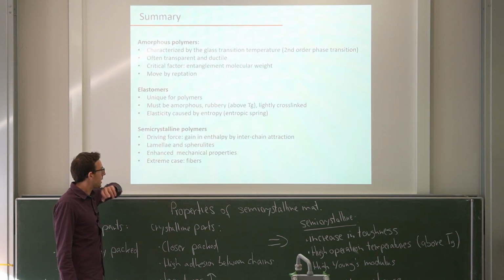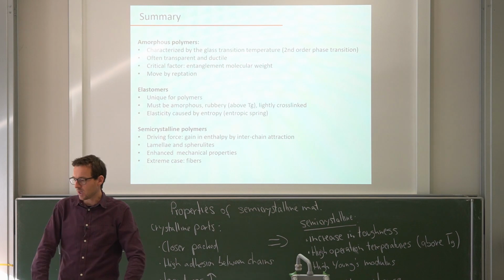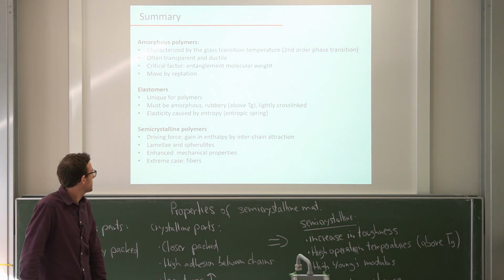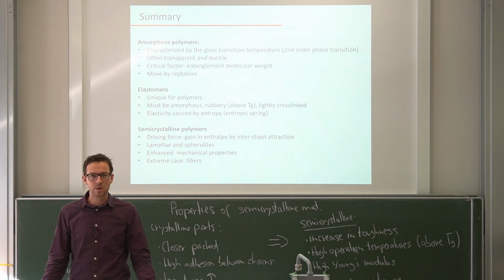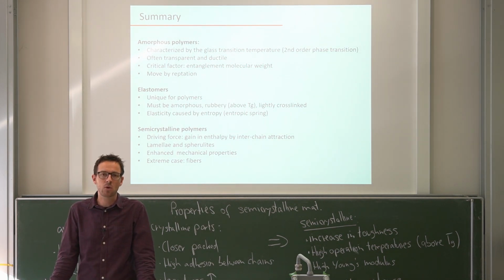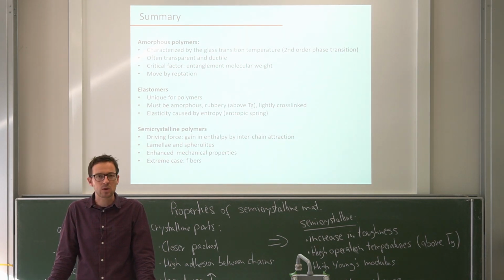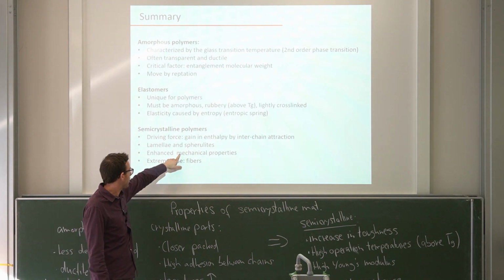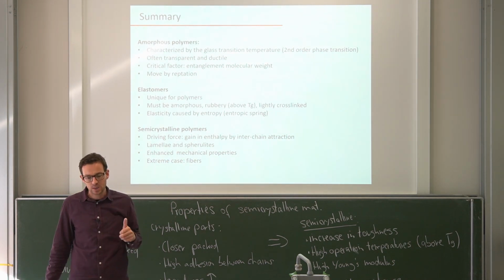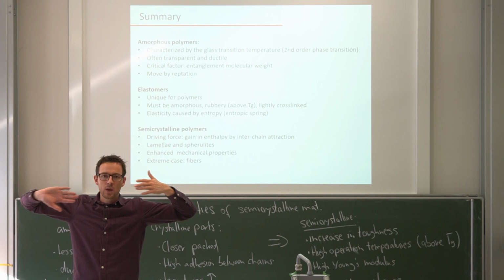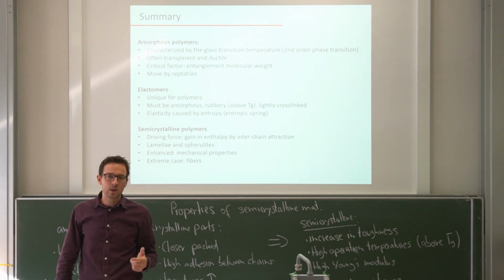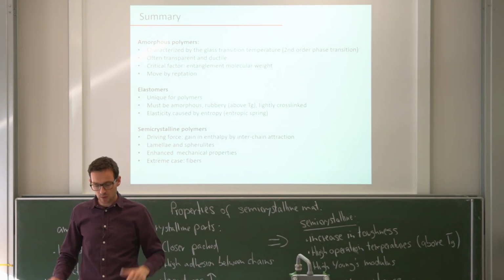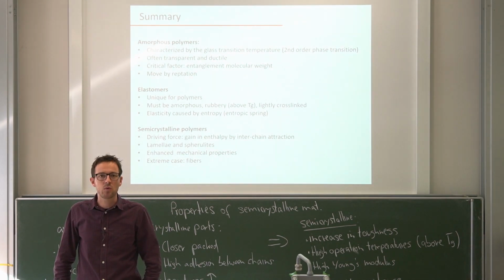We've seen that they crystallize in lamellar structures and can potentially form spherulites. And then we've seen that a lot of properties change for semi-crystalline materials simply because they combine both properties of amorphous polymers and crystalline materials. For example, the mechanical properties are strongly enhanced. So we've discussed that they're much tougher because we now need to dissipate energy by destroying all these polymer crystallites. But we've also seen that they're more chemically resistant because it's much more difficult to dissolve a crystal compared to an amorphous material.